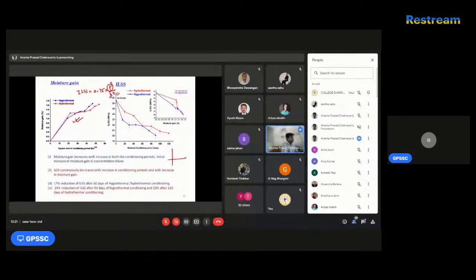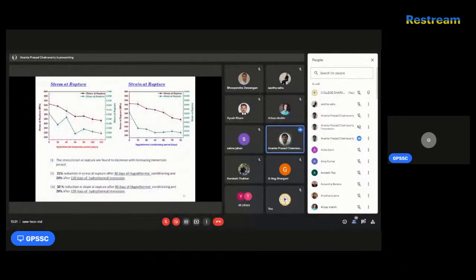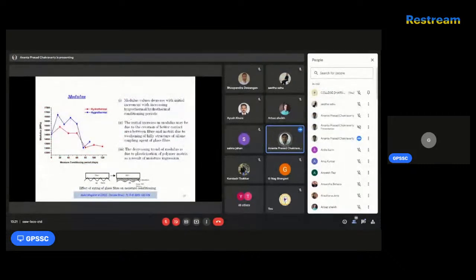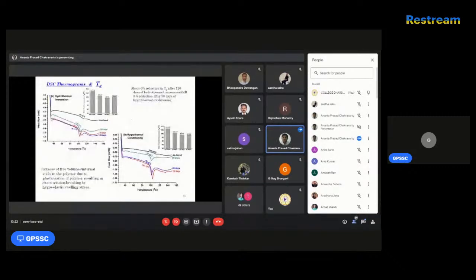So from the load versus displacement graph, let us say this is your maximum load, that is stress versus strain. You can use this as the maximum load P, and the breadth and thickness are already with you. Then you can calculate ILSS. Then you can see the trend, why these are decreasing or increasing with respect to increase in moisture gain, due to plasticization and other deteriorating factors. Similarly, you can analyze stress at rupture, strain at rupture, and obviously modulus, and from the 3-point bend test all those data can be obtained and utilized to understand the core mechanical properties.